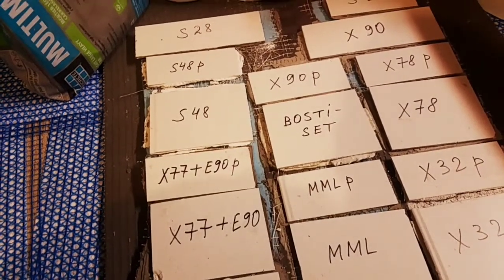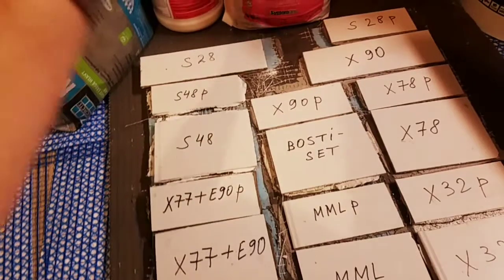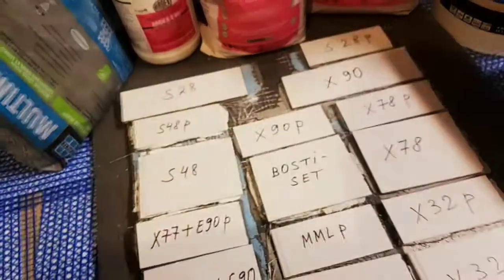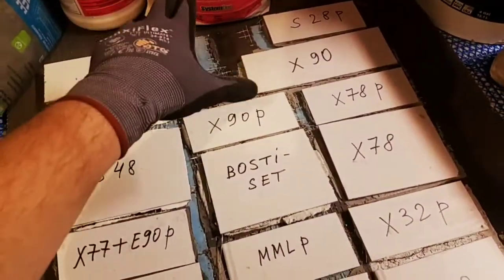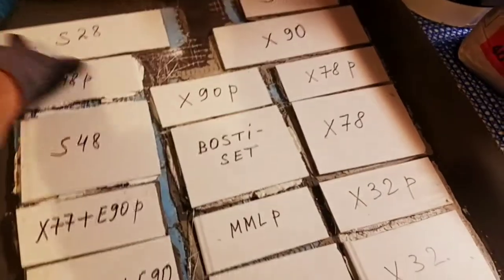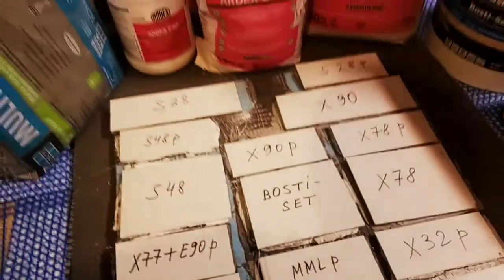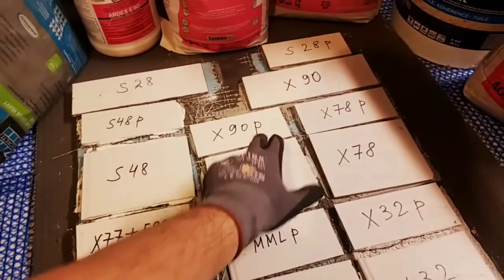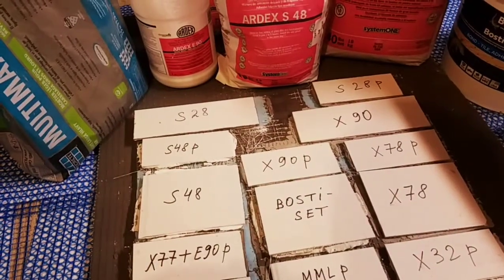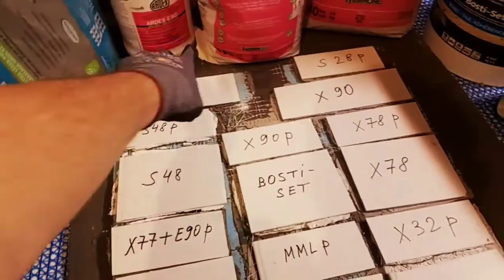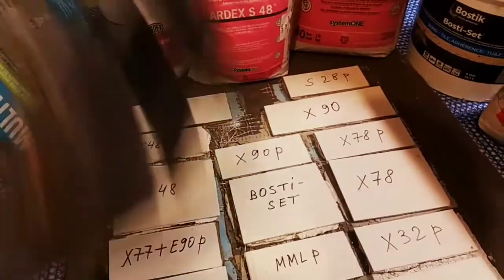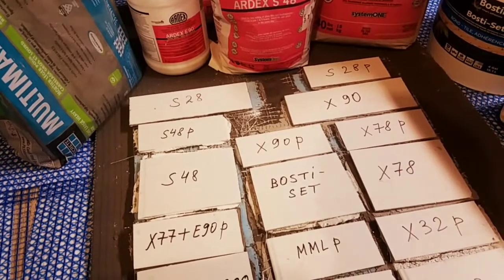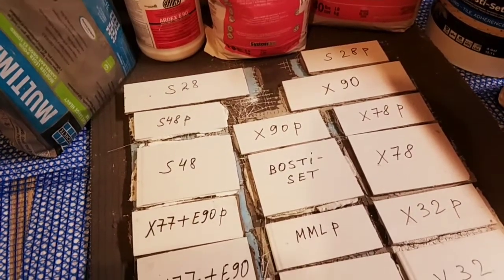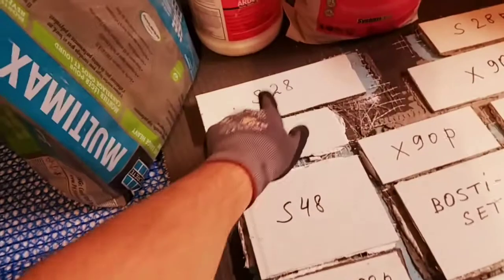My expectations were that most or all cementitious mortars that I would install directly to resin backing would not produce proper bond. I was surprised that two of the cementitious mortars still showed great adhesion to the resin backing on Dekton Slim 4mm thick panels. And I want to start with the first sample that I removed.